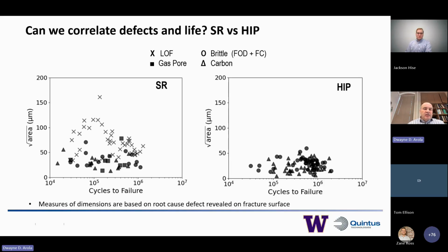But then in the case of the overall data distribution, we don't at all. In the HIP treatment condition, we don't see a trend at all. I also point out that the square root of area dimension here is largely less than about 50 micrometers. So reduction overall in size, of course, and no trend. So this is not to be expected. That means a trend between these types of defects depends potentially on location, but also the mechanisms which are responsible for the percolation of these defects into a well-defined flaw that results in failure.